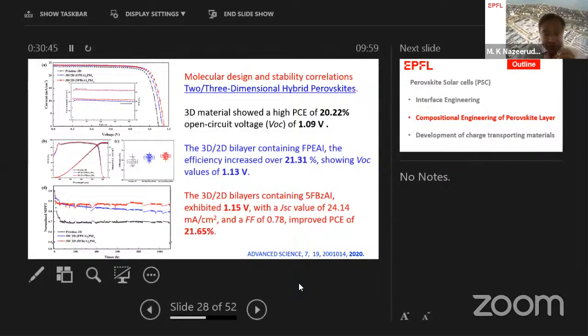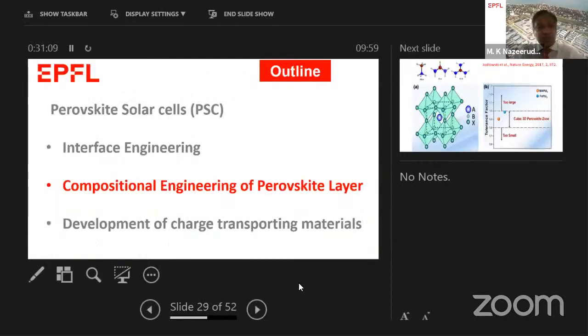So the reference sample is a pure three-dimensional perovskite, and now we have a red line, which is the pentafluorobenzylamine-involving two-dimensional perovskite cation, and it shows extremely stable performance. So we classify this as interface engineering to enhance the stability of the perovskite solar cells. In the next few minutes, we will discuss the compositional engineering of the perovskite layer.